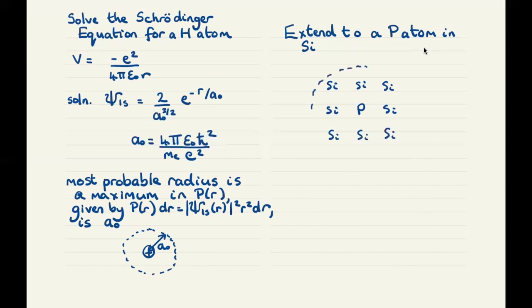And the most probable radius, we call this time the hydrogenic radius, a sub H. Our potential changes from the potential for a hydrogen atom because the additional positive charge is now screened by the dielectric constant of silicon. So the potential is reduced by 1 over the dielectric constant of silicon.